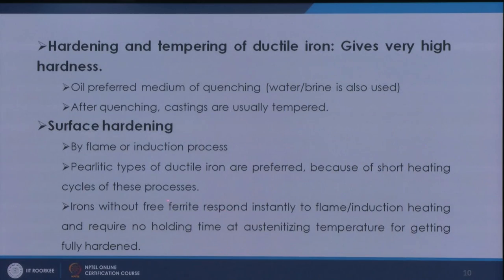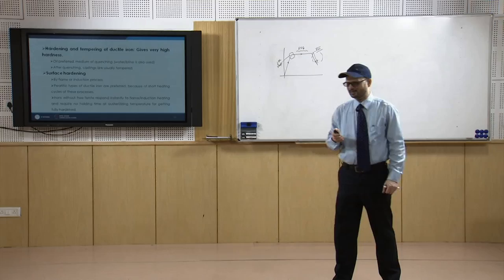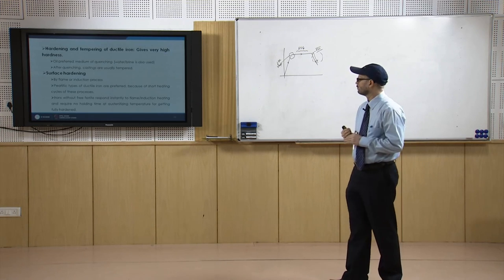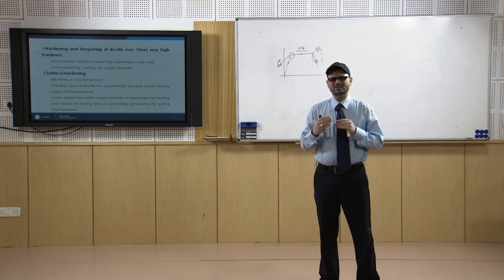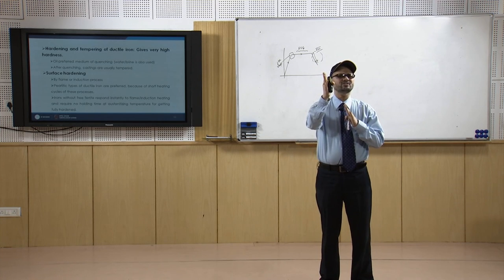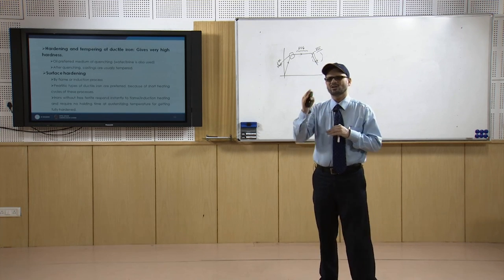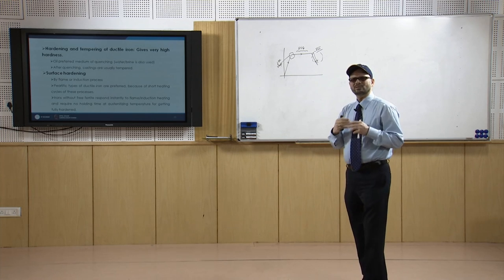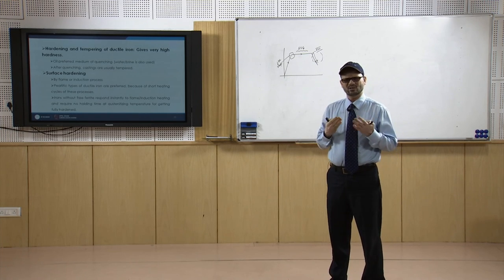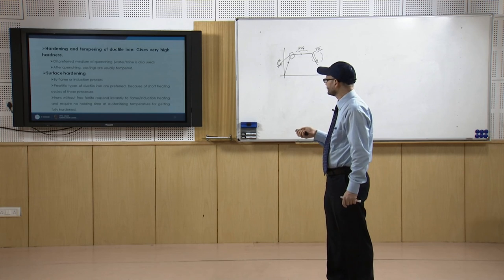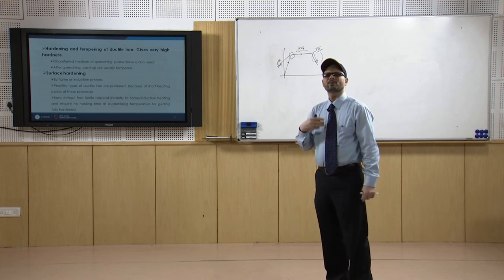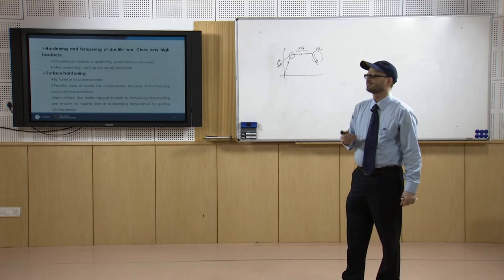Iron without free ferrite responds instantly to flame or induction hardening and requires no holding time at austenitizing temperature for getting fully hardened. So, this point tells that if there is no fully ferritic matrix, you go to the austenitizing range and without much holding you can cool, so that you get sufficient hardness. That is why these perlitic types are preferred over the ferritic type of ductile iron.